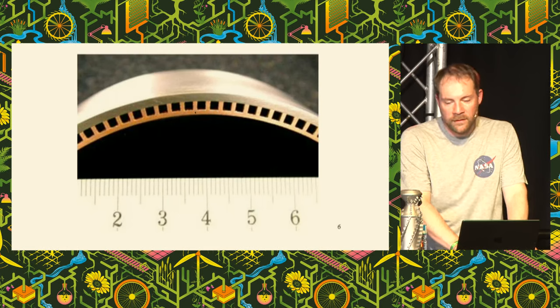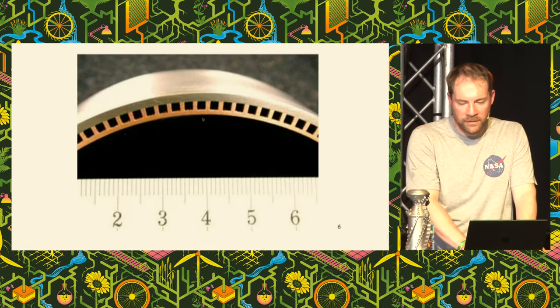Copper is a very good heat conductor. It's good at transmitting heat from inside the combustion chamber into the cooling channels, but it's not very strong, so you often want another material on the outside, like Inconel, which has a bit more strength. Then you have to somehow melt all of the wax out of the cooling channels and then clean them all up, and then you're ready to put your rocket engine into service. And this whole process can take, as I said, weeks to months of skilled technician time, and it's part of the reason that conventional rocket engines are really very expensive to produce.